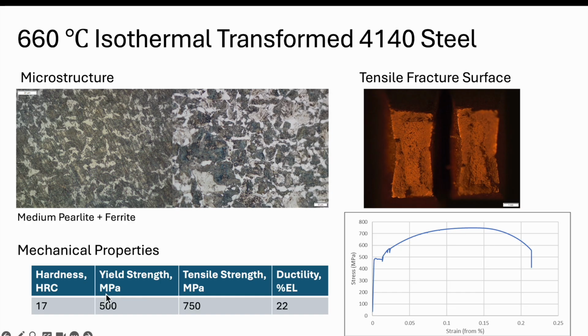And so our strength again continues this trend. Strength goes down to 500 for yield, about 750 for tensile. The ductility continues to go up, so we're about 22 or so, and the hardness goes down, so we're at about 17. And so everything but the hardness was taken from our engineering stress strain over here. And again, we see the yield point. So for perlite, we have this yield point, and again, substantial ductility that we see here.